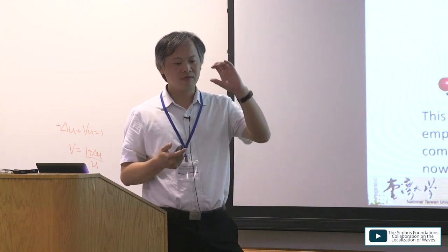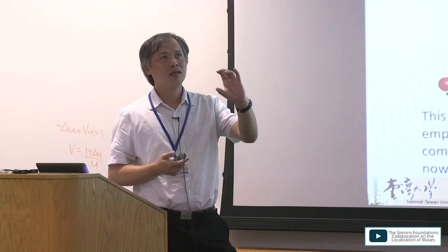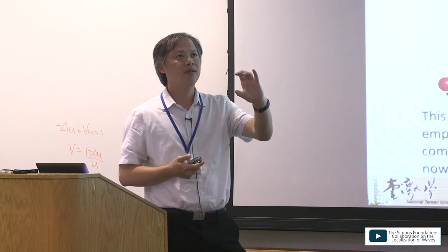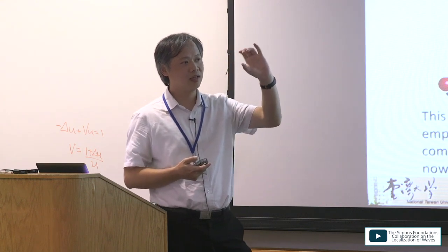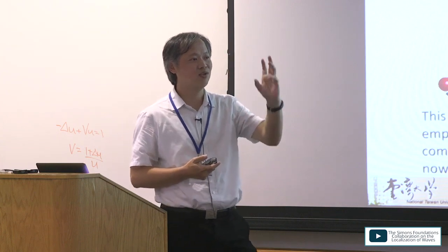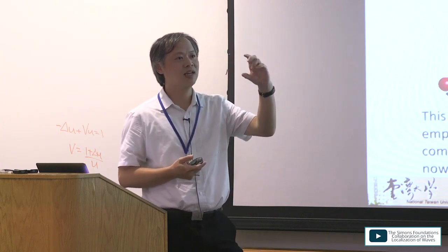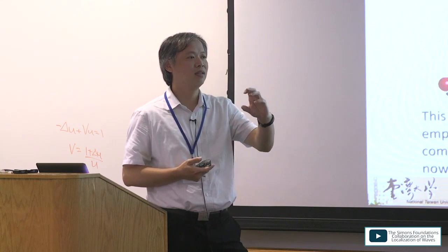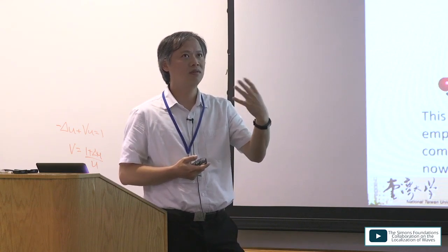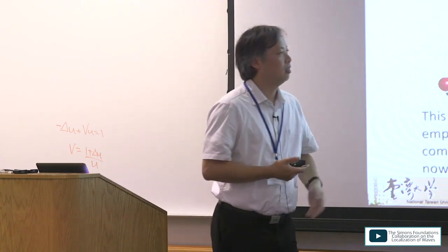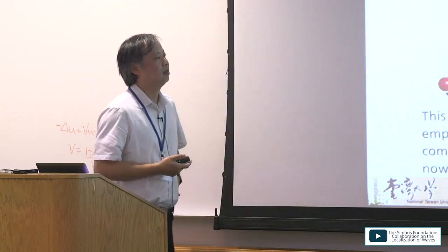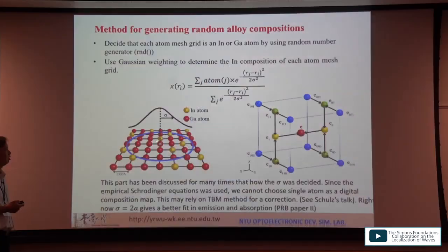But the problem is that if you only have one atom, a single indium nitride atom is not a crystal, so you cannot use the 0.7 eV band gap. Effectively, you need to reconsider something; I think the TBM model may give you more description.